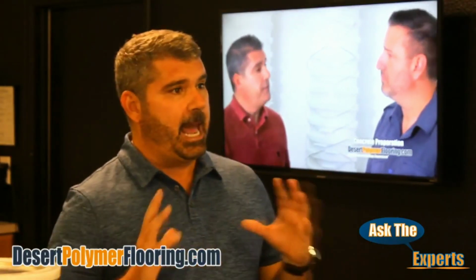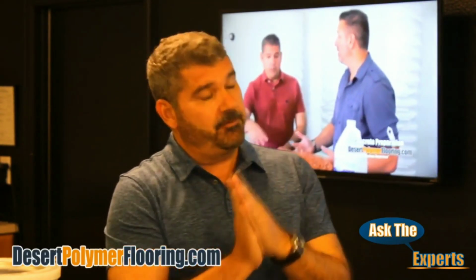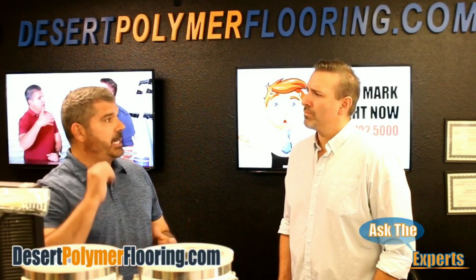People ask this question all the time: can I use Poly 250 as a primer? Yes. In fact, Poly 250 can be used in different ways. One, it could be used as a primer coat before you put on a two-part polyaspartic, say inside a mechanic's bay. Or Poly 250 could be used as a tie coat. When you see an aliphatic urethane, you can have this high shine where you have minimally profiled areas. Poly 250 is designed to be a tie coat, meaning it will bite into that by adding a quantity of acetone. Usually they require about 50% acetone to 1.5 gallons. So with that, you could go on a minimally profiled coating, and it will bond. It has adhesion promoters in the product, and it's a proprietary chemical, and when it goes on, it bites. So yes, it can be used as a primer.